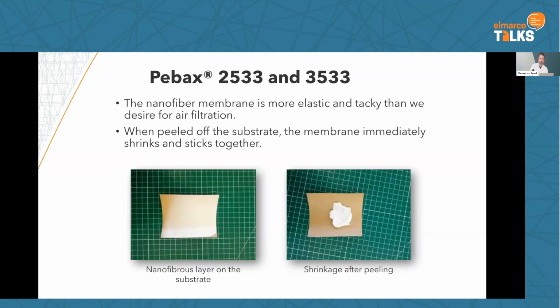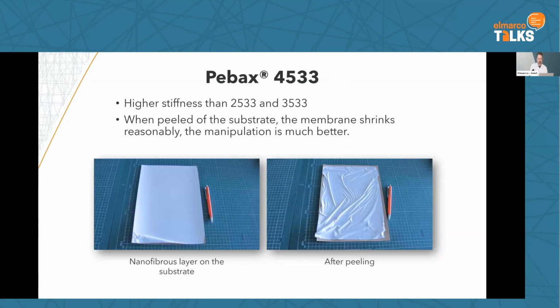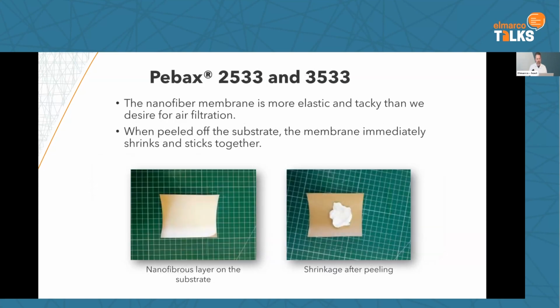So the initial results, we looked at the first softest grade 2533, spun very well, and both the 2533 and the 3533 electrospun quite well. For this application, we weren't looking for this much elasticity and tackiness, but for other applications, it could serve well for that. And I apologize, I can't share every result from everything we've been doing with the Pebax, because a lot of them are related with our different customers and partners. But in this case, for this application, looking at air filtration, we wanted to look at a slightly harder grade, which was the Pebax 4533. And you can see before, whenever you peeled the membrane off, it became quite tacky and sticky together, which again, I said, could work well for certain applications.